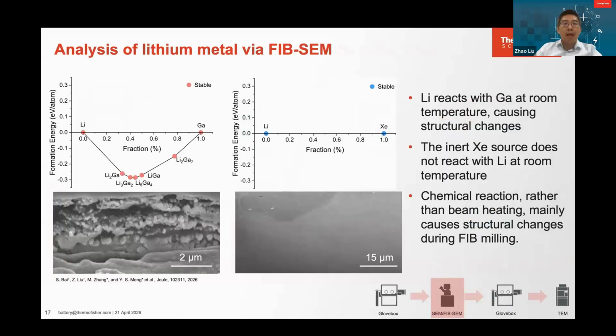So the first step is to analyze the lithium metal inside the FIB-SEM. The image on the left shows what happens if you use a gallium FIB to mill the sample at room temperature. Because of the gallium, lithium will form stable phases during the alloying process. It can actually damage the lithium metal sample and form a lot of porosity, so the pristine state has been changed. In these cases, you have two parameters. One is the reactivity between the lithium and the gallium. Another is the heating damage on the samples.